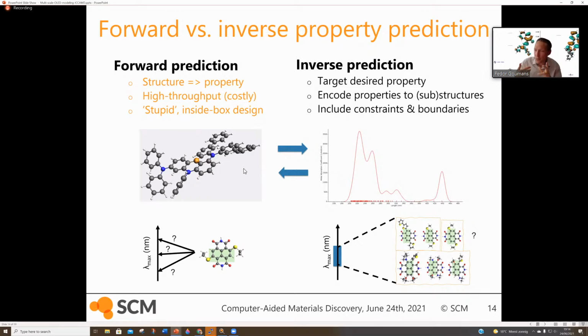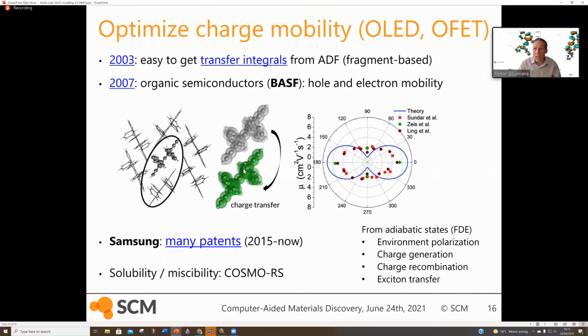In 2003, there was a paper where people were interested in charge mobility in polymeric systems, and they found out that in ADF, because we use fragments as an input, you can define two different fragments and then calculate the molecule in that fragment basis, and the Fock matrix elements that you get out of that correspond to hopping events. So the HOMO corresponds to a hole hopping event, the LUMO corresponds to an electron hopping event. Again, that was picked up by our neighbors in Germany, by BASF, who then thought, okay, then this we can use for being able to predict the electron hole mobility in a range of organic semiconductor materials.